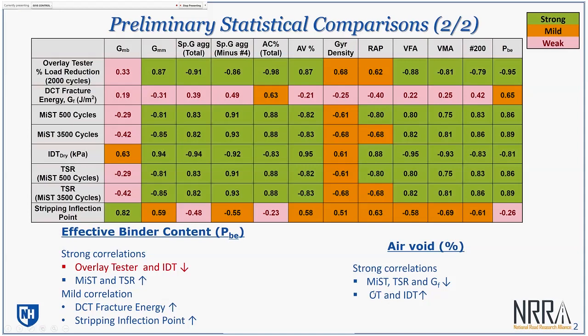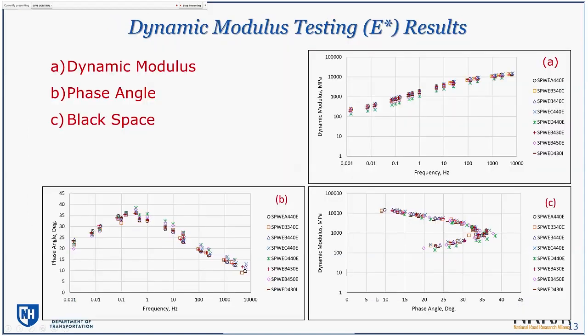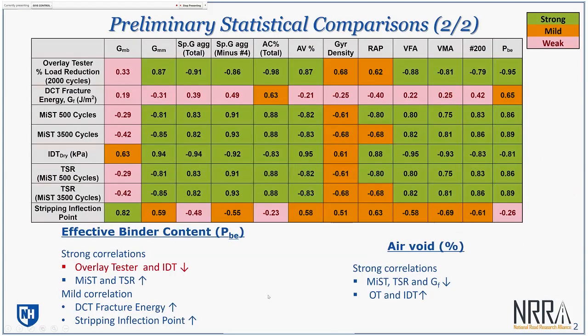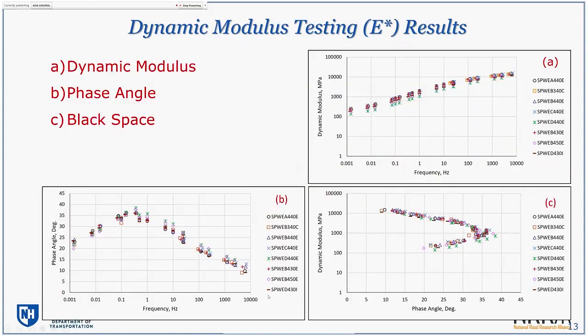On the air void side, we saw that increasing air void was resulting in lowering of your durability, which also makes sense, but also lowering of your fracture energy, versus on the overlay tester side, increasing air void was resulting in improving of overlay test results and indirect tensile strengths. So again, it's fairly early, so I don't want to spend too much time on those, because really what we will be doing is making these type of comparisons between field performance and these properties, rather than these properties and volumetrics only.